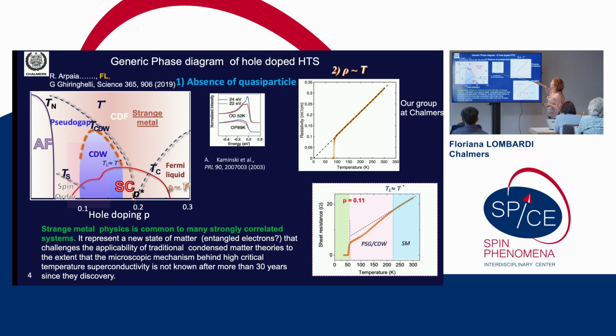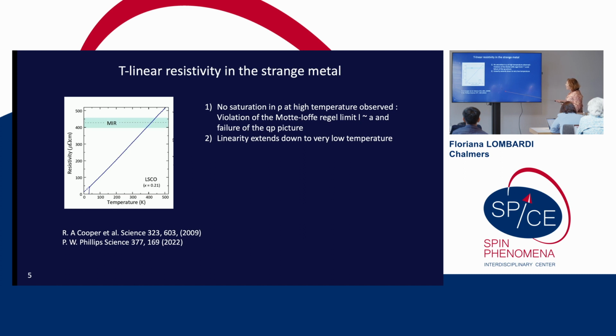And in addition, in the strange metal phase, one also gets fluctuation of charge, which we call charge density fluctuation, and that we discovered a few years ago. So it is also a peculiar state of matter. The way that I said before is that you have this T-linear resistivity that extends for several orders of magnitude, even when the mean-free path is comparable with the interatomic distance. And this is a further hint that the quasi-particle picture